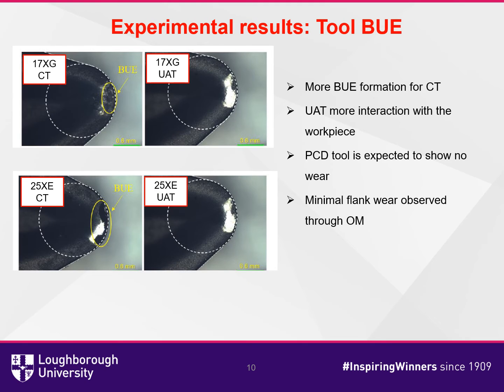Optical microscopic images of the carbide tools are shown. Clearly there is more BUE occurring in CT than UAT. The black area in BUE is predicted as the wear of the tool coating. UAT tends to have more interaction with the workpiece, showing more white area which is assumed to be aluminum. The flank wear cannot be observed through the optical microscope, hence requires further investigation.